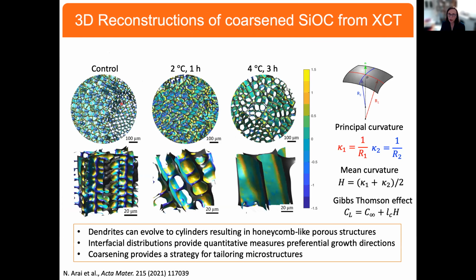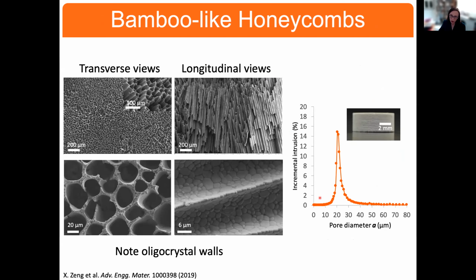And we can also follow this with X-ray tomography, where we, in 3 dimensions, now watch these porous structures evolve to these honeycomb and cellular type structures, where the dendrites result in honeycomb porous structures through coarsening. These X-ray techniques allow us to follow this quantitatively and look at the mean curvature and how it changes, and use this now as a second strategy to tailor the microstructures. Now, when we do this, you see that the pore walls are now single grain thick.